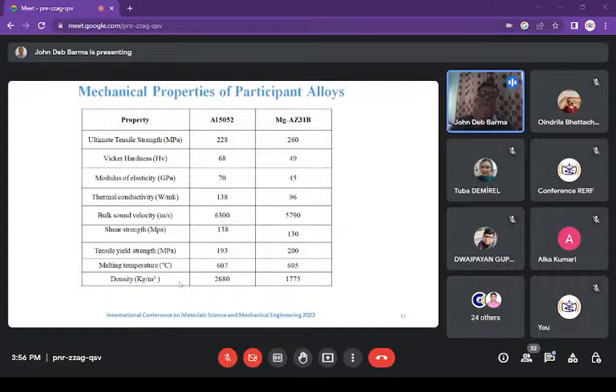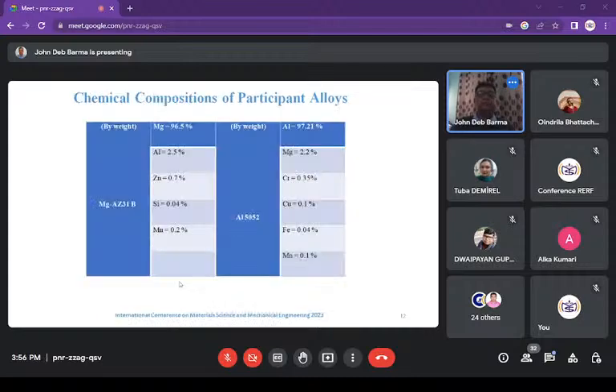Now these are the mechanical properties of the participant alloys. You can have a look. And these are the chemical compositions of the participant alloys. So as you can see, if we talk about AZ31B, it contains magnesium, as I have already mentioned. This is a magnesium alloy, 96.5%. It contains aluminum also, and zinc, silicon, manganese, etc. Similarly, these are the aluminum alloys, AL5052, and you can see that it is 97.21% aluminum.